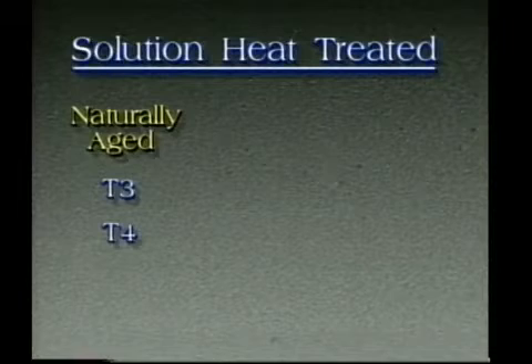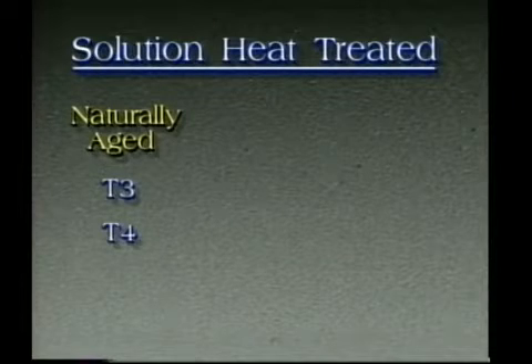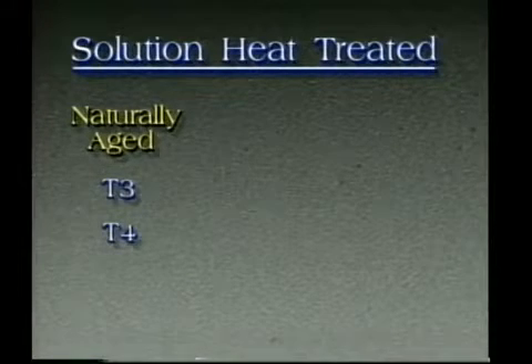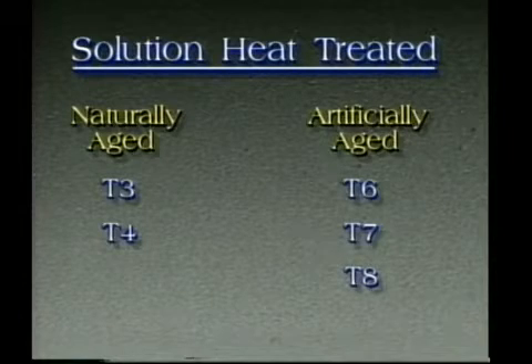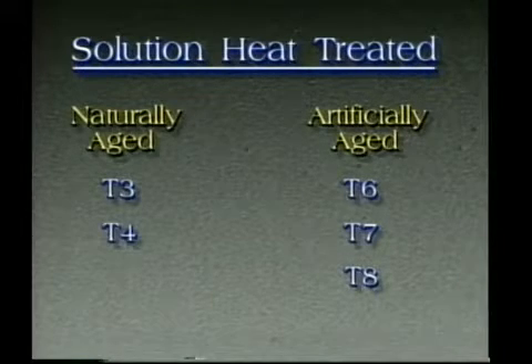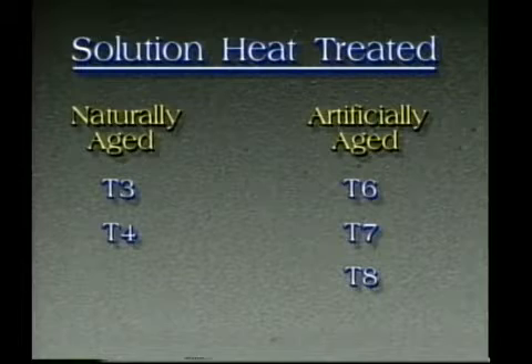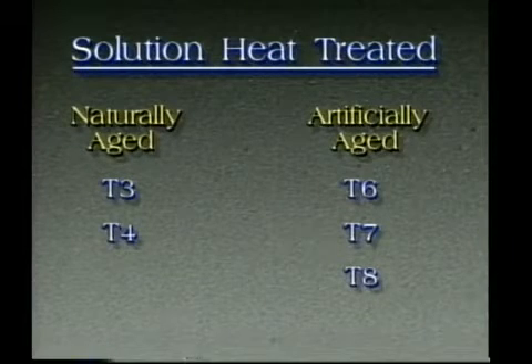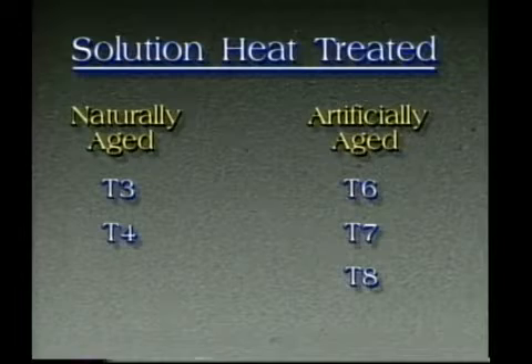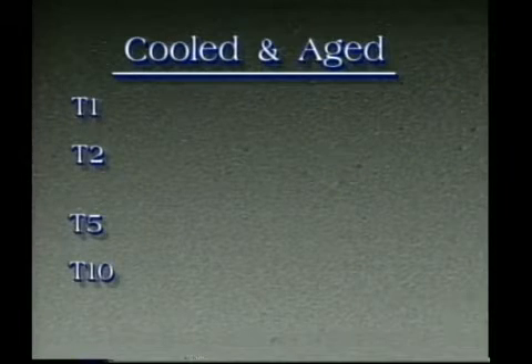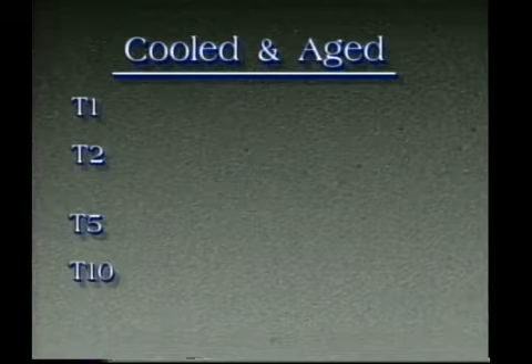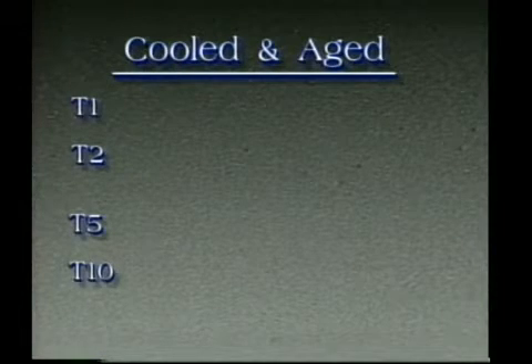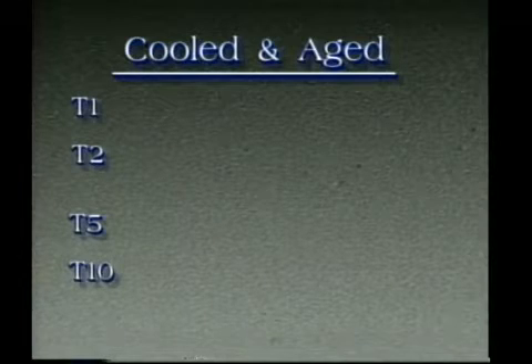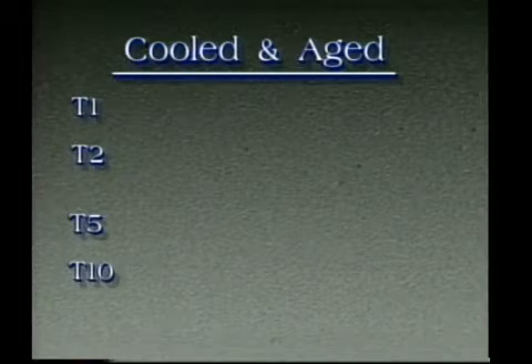T3 and T4 are alike in that they both are solution heat treated, quenched, and naturally aged to achieve the required properties. T6, T7, and T8 are alike in that they are all solution heat treated, quenched, and artificially aged to achieve the required properties. T1, T2, T5, and T10 are less common tempers because they are not solution heat treated. They all represent material that has been rapidly cooled after some fabrication process and then aged.